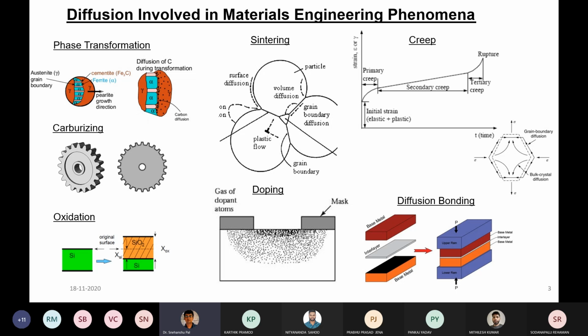In all the cases, if you see pack carburization, diffused carbon is important for the nature of the case. And in gas carburization, there is also carbon diffusion, but the process will be different with respect to the material you are taking. In pack carburization, solid state diffusion will take place. If you look at gas carburization, then carbon monoxide and those gases are used. And this carburization process requires a very good amount of diffusion of carbon inside the surface of the particular product made by low carbon steel.